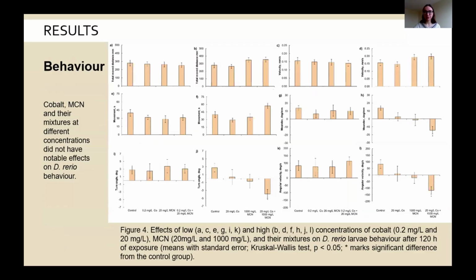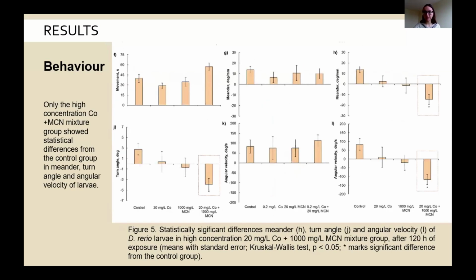And lastly, we checked the behavior of Danio rerio zebrafish larvae. Here I put a graph of different behavior parameters, but to sum up, cobalt, MCN, and their mixtures at different concentrations did not have very notable effects on the behavior. There were only 3 parameters that did show statistical differences that you can see here. Namely, only the higher concentration of the cobalt plus MCN mixture group showed statistical differences from the control group in meander, turn angle, and angular velocity of larvae. There were some differences in other groups, however, they were not statistical.